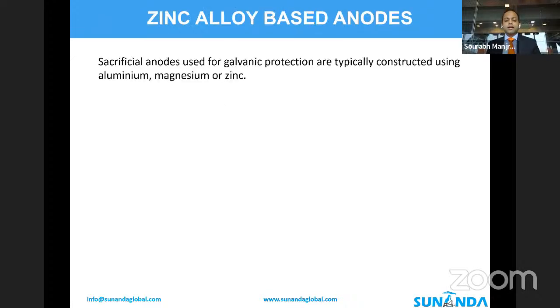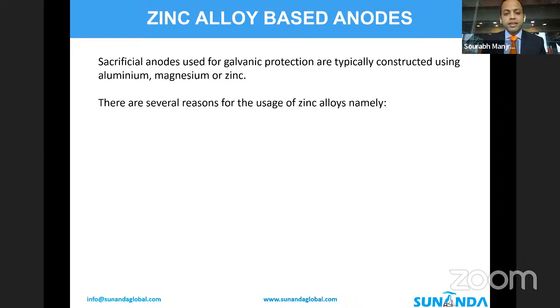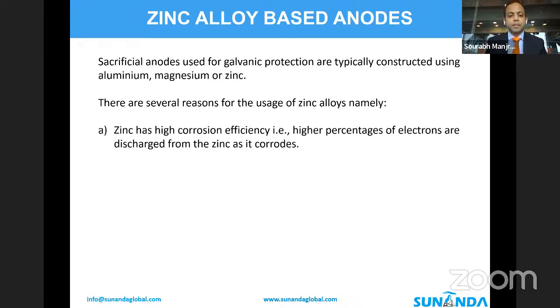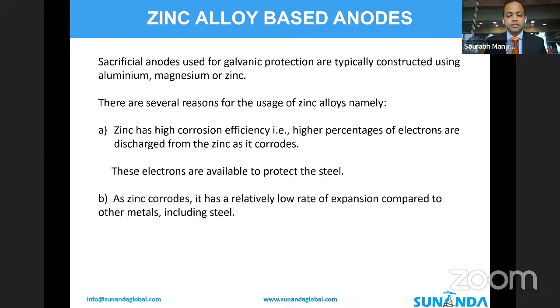So typically, sacrificial anodes used for galvanic protection are manufactured using aluminium, magnesium, or zinc. There are many reasons as to why zinc is used or was used in these particular cases. Zinc has a high corrosion efficiency, that is, higher percentages of electrons are discharged from the zinc as it corrodes. These electrons are available to protect the steel. As the zinc corrodes, it has a relatively low rate of expansion compared to other metals, including steel.